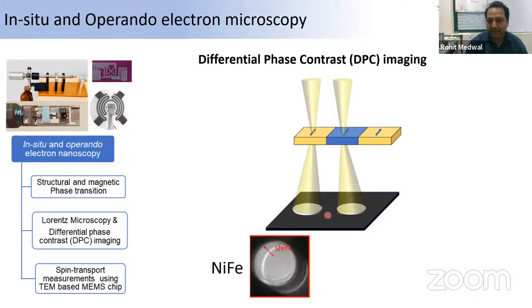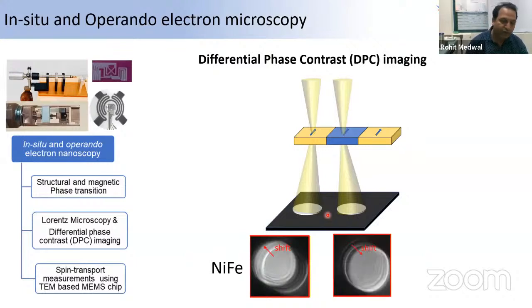And this is my live example, which we have shown here in the permalloy, which we are working on. This is a bright field disk, which should be undisturbed without the ferromagnetic material, but this is the shift in the bright field disk after it has passed through the magnetic domain here. When we have the domain in a different direction, we have exactly the opposite shift in the bright field disk of the electron beam, which is being focused on the fluorescence screen. So this is how we use it, and based on the shift of this bright field disk, we can estimate the magnetic moment in the ferromagnetic materials, and we can see the direction of magnetization.